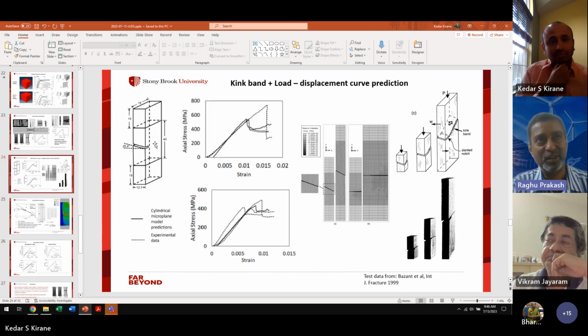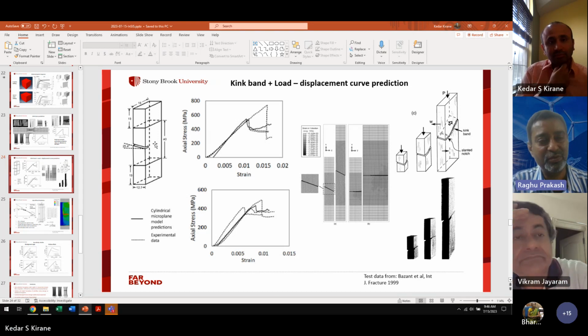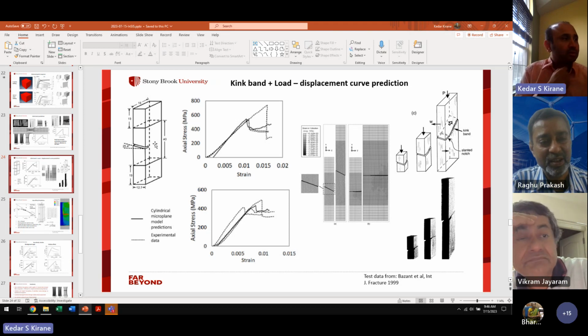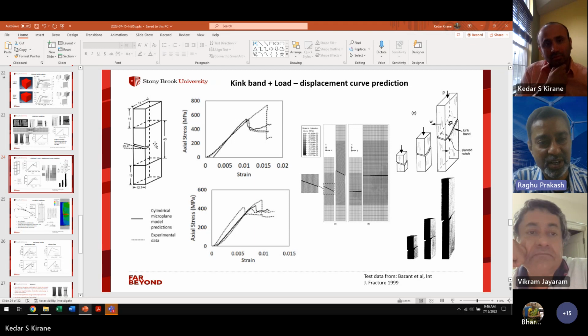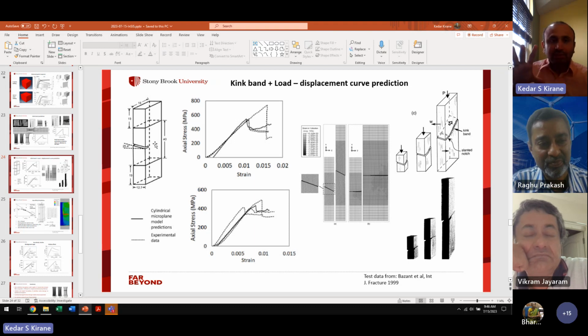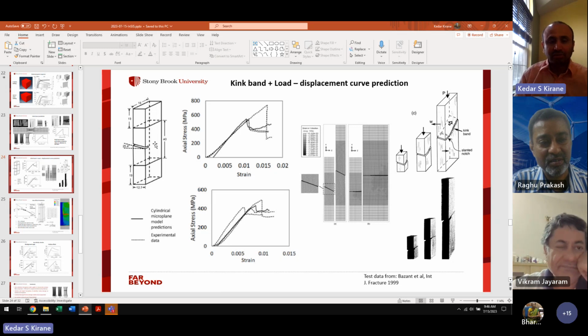Did you have to use any kind of spherical seating for ensuring it's pure compression during these experiments? Like normally in the case of metals, when I want to do a pure compression test, I would use a spherical seat so that any misalignment in the planes can be taken care of by the spherical seats. See, actually, no, we have not done that. There is a fixture called the CLC fixture, combined loading compression fixture. It is a combination of end loading and shear loading. That is an ASTM standard for compression tests, so we are using that fixture. We are not using the spherical stuff that you mentioned.